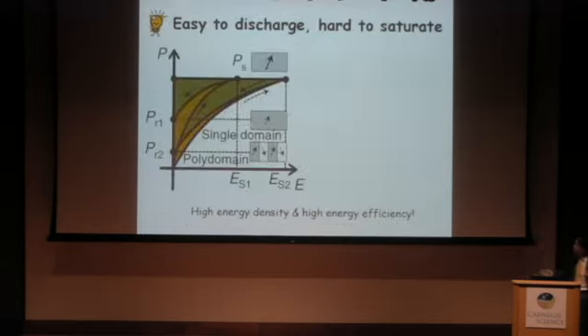Again, I just zoom in on the picture I showed you earlier a little bit. If you begin with a polydomain with a head-to-tail configuration, the apparent remnant polarization is close to 0, and when you apply a field, you change the polydomain structure into close to a single-domain structure. But if you discharge it, because these domains are equivalent and remnant, they would like to stay in this head-to-tail configuration, and you can discharge most of the energy that you initially put into the ferroelectric capacitor. So that's the idea from the domain engineering point of view. We would like to have this kind of polydomain structure to begin with.